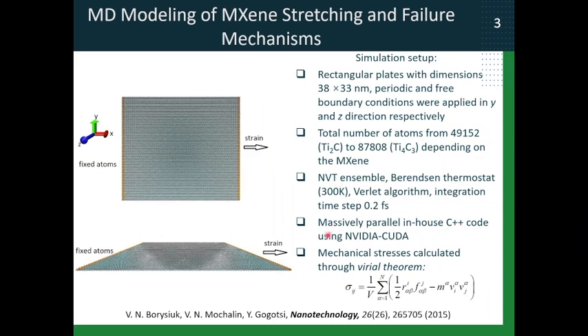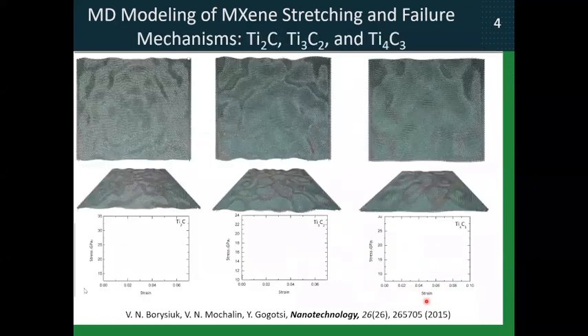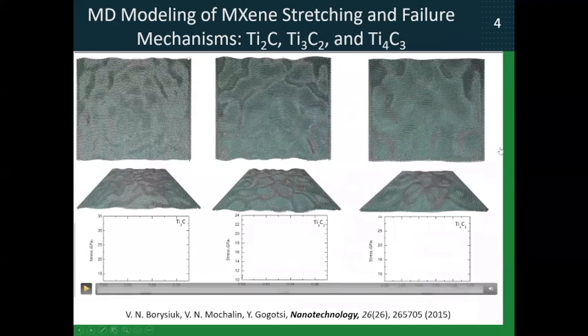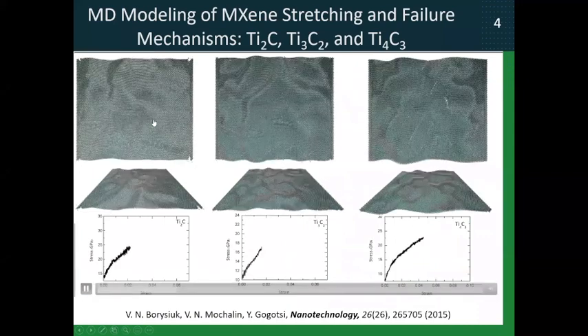So it's massively parallel code. And mechanical properties we calculated using virial theorem. For example, stresses were calculated using this expression. This is a very well-known procedure. The advantage of using computational modeling to simulate MXene behavior is that you have full control and full information about what is going on in your material at the atomistic scale. So here I show a movie of stretching of 3 different MXene monolayers.